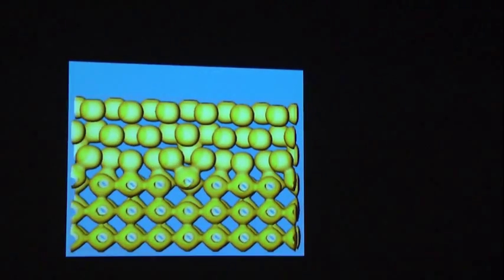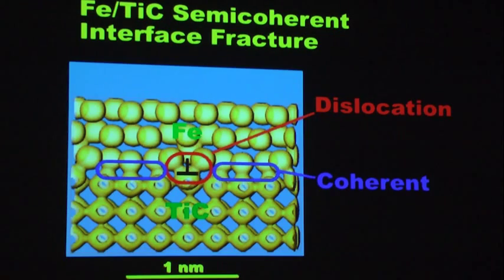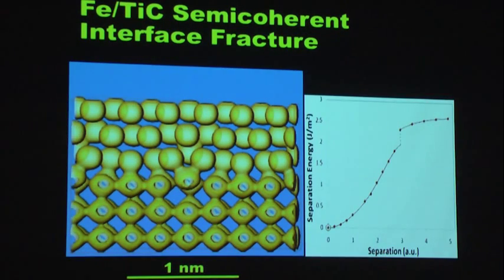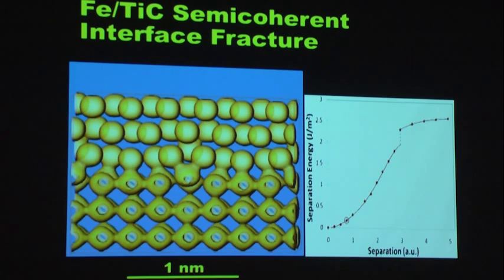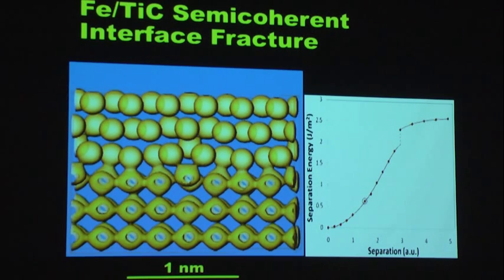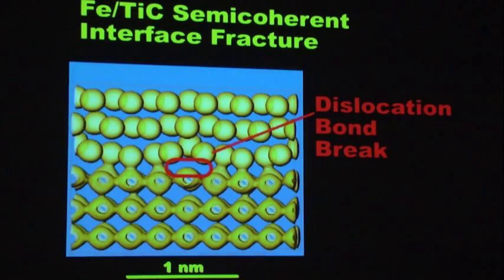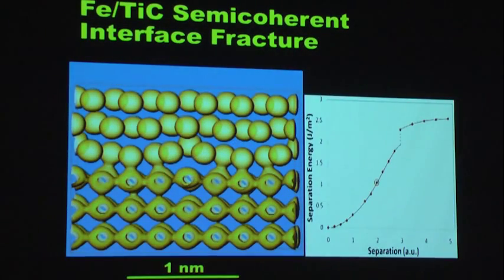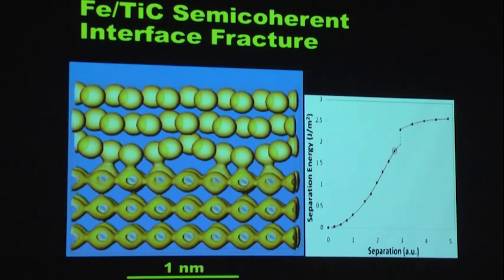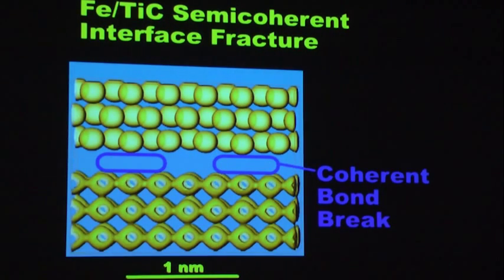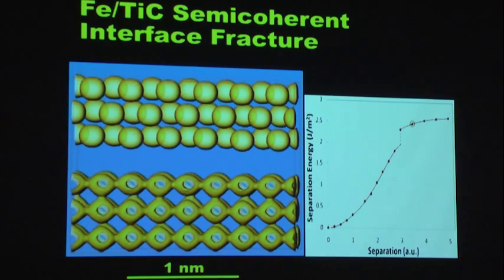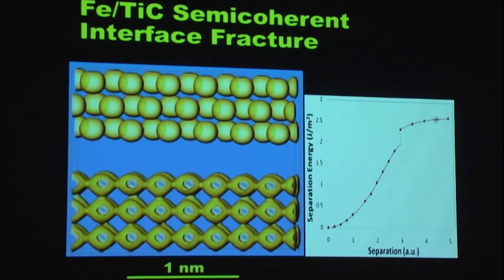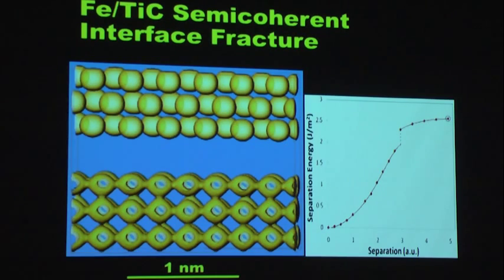Now, moving up to those submicron particles, here what we're interested in is the interfacial adhesion and how it affects fracture processes. And here we've been able to scale up our DFT all-electron calculations to look at a semi-coherent interface between iron and titanium carbide and calculate the work of adhesion, where we find that it comes apart first at the dislocation before spreading to the coherent patches, thusly. That then gives us the work of adhesion that we can put into continuum simulations of the microvoiding process of these particles.